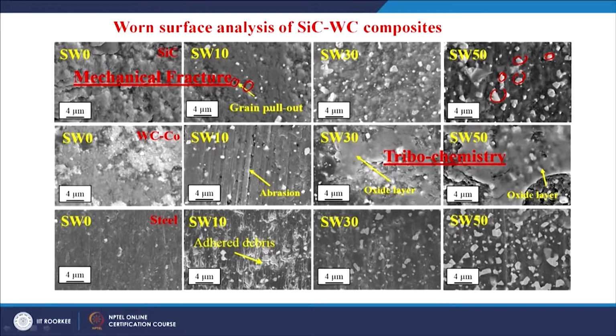But as the tungsten carbide content is increased, you can see the presence of a particular layer. This layer dominantly covers the surface, particularly when you have the highest tungsten carbide content. But when you see the composite worn surfaces which were worn against steel, again they show the debris and then fracture and the removal of these tungsten carbide particles. So, there is a change from the mechanical fracture to tribochemistry when there is a change in the tungsten carbide content or there is a change in the counter body.